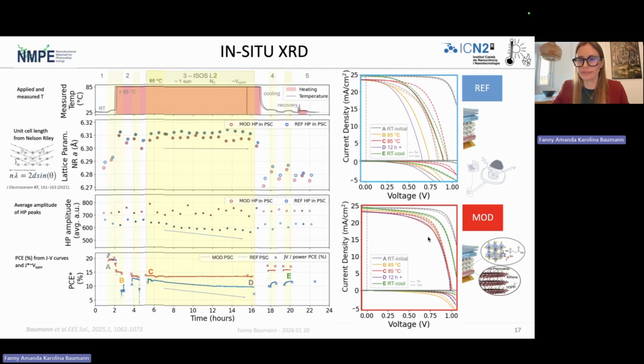So here you can see all the IVs together, and in the end, the IV curve of the recovered modification and the reference coincide quite well with what we saw in the little slide operational testing. So it was really good that we could do these two parallel tests and really compare one to the other. That provided a lot of value for us to verify and make sense of what we're seeing here.